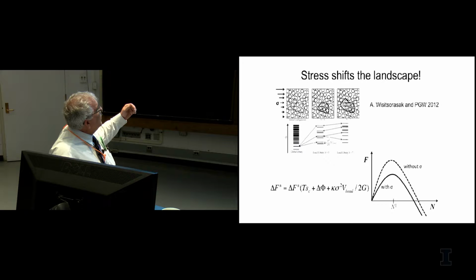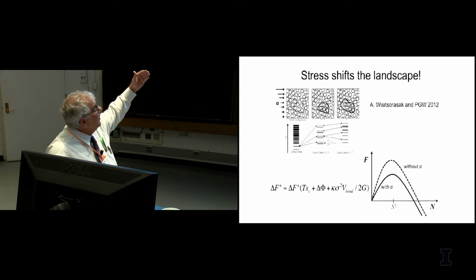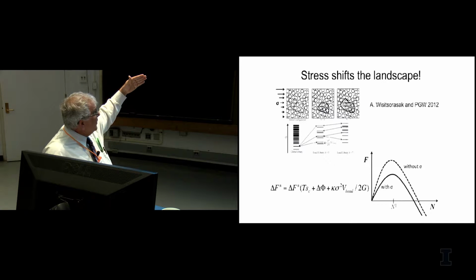And you can see from the Prince Rupert drop experiment that if there are stresses, there's stored energy. Well, if there's stored energy, then when you try to reconfigure a region, you gain back not only the configurational entropy of all the other states. If the material was frozen in and was actually frozen glass, you now could access states that are lower in energy than you started out with. That's part of the so-called aging process.